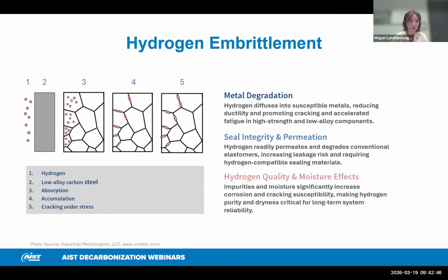In image 4 here, you see the accumulation. So the hydrogen migrates to microstructural defects such as grain boundaries, where it accumulates and weakens the atomic bonding. And then in image 5 here, this is under tensile stress. So these weakened regions initiate cracks that propagate rapidly, causing brittle fracture at stresses below the steel's yield strength.